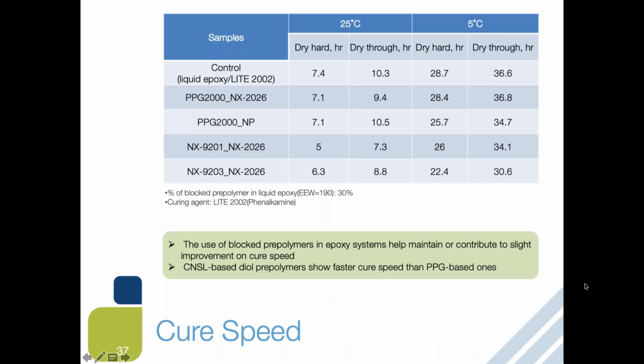So in this case, the control system has a liquid epoxy with Lite 2002, and Lite 2002 is a phenalkamine curing agent. Phenalkamine curing agents are known for good low temperature cure and good corrosion resistance. So these are the control, and then we add 30% of blocked prepolymer, PPG 2000 based prepolymer, and also CNSL-based diol prepolymer.